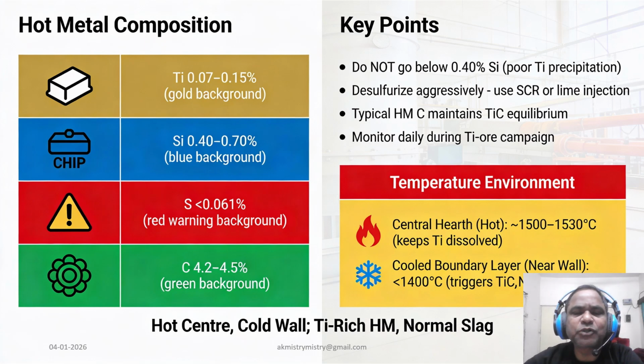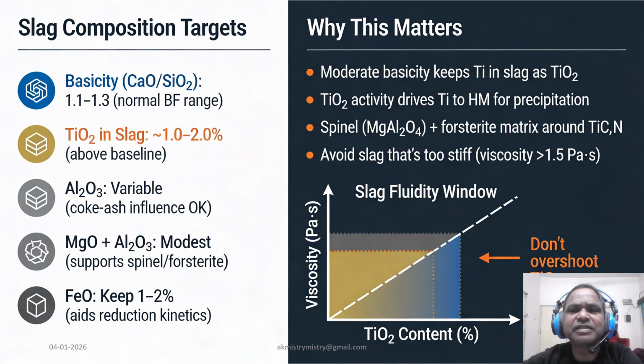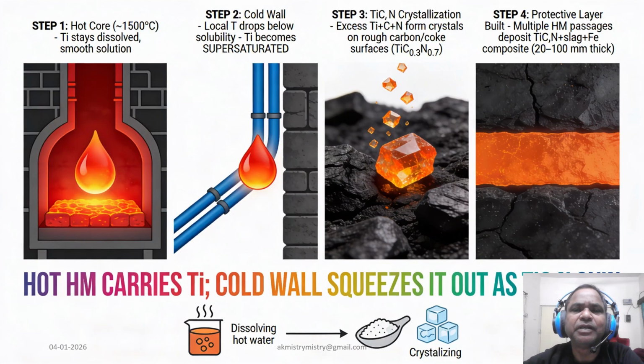Now coming to the slag composition, this slag chemistry is just as vital as the metal. We maintain basicity between 1.1 and 1.3 to keep titanium in the slag as TiO₂. We aim for a TiO₂ level of 1% to 2% above the baseline. It is critical not to overshoot this level, and if the slag becomes too stiff with a viscosity over 1.5, it will disrupt the furnace tremendously, and it will hamper production and productivity.